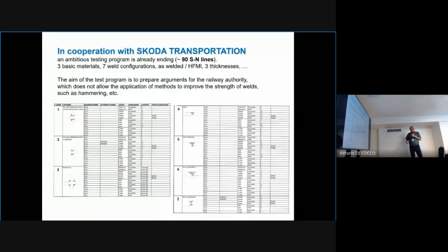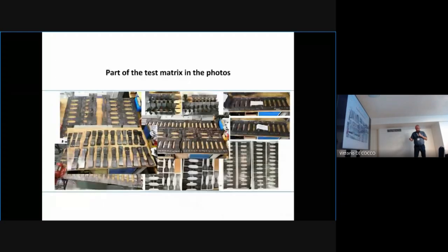Now I will speak about the 4 activities in this area. In cooperation with Škoda Transportation, we prepared a very huge testing program, which is already ending. At the end of the program, we will have 90 S-N curves for 3 basic materials chosen by Škoda Transportation, 7 weld configurations that are used in the construction of vehicles of this producer, in the condition as welded, and this without and with HFMI. We studied 3 thicknesses of steel plates. It means we have a very huge testing matrix. You can see the back of the test specimens from our lab.